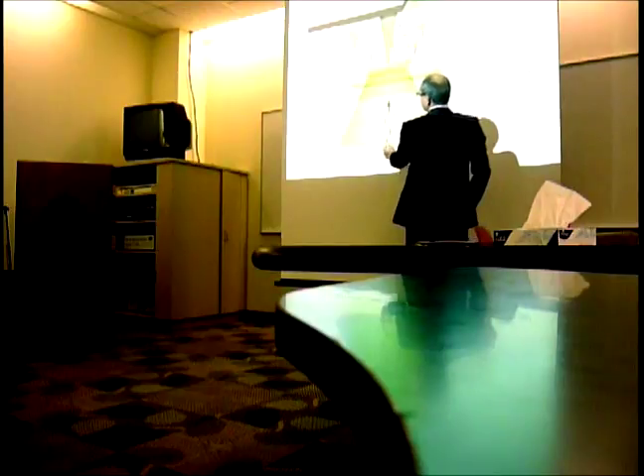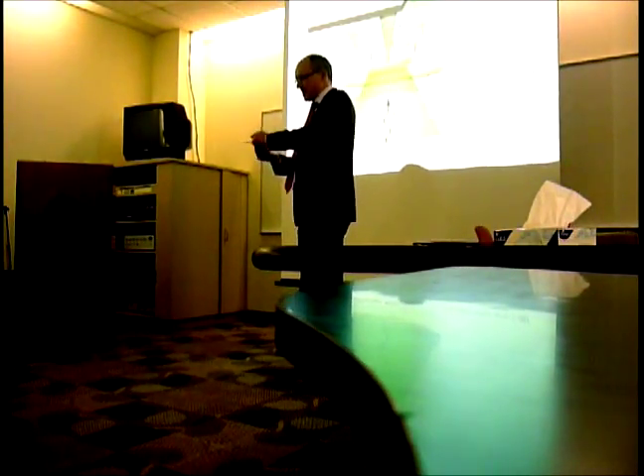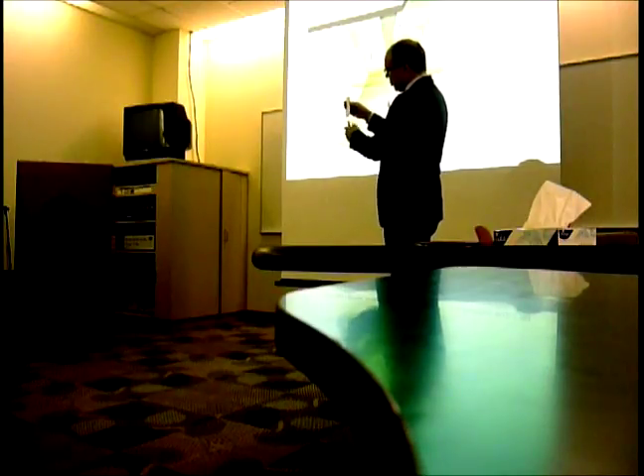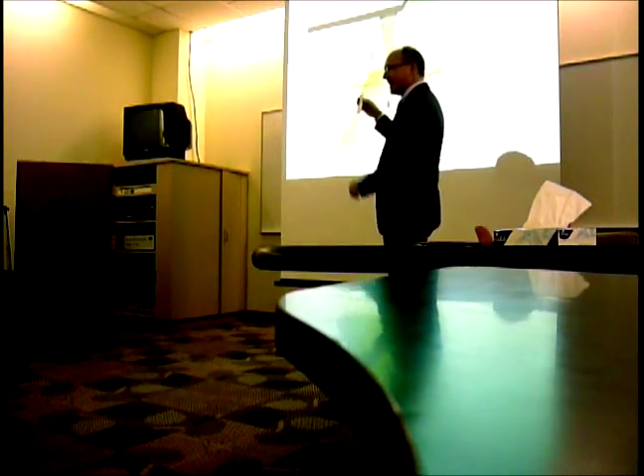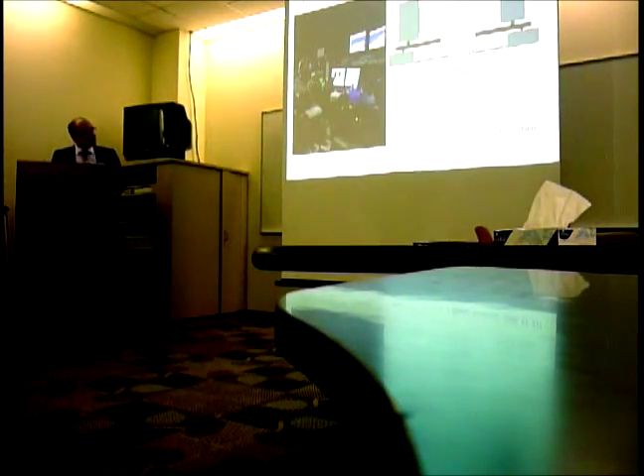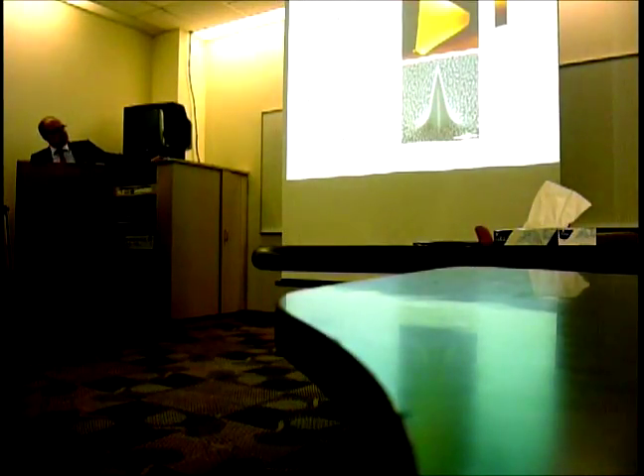What you then do is you excite it with laser light, and then you have here a tip. And this tip is what I explained. It's not anymore this surface, but now you can put it like this. This is the tip. So what you do is you shine. Here you have your gold plated thing. You shine on it, and then at that moment you enhance locally your signal. So that would mean that we should be able now to do this. Well, here I show you the setup, so it's more difficult than I showed with these things. Just to show you what it is all about, here you see the sharp tip, and when you shine light on it.